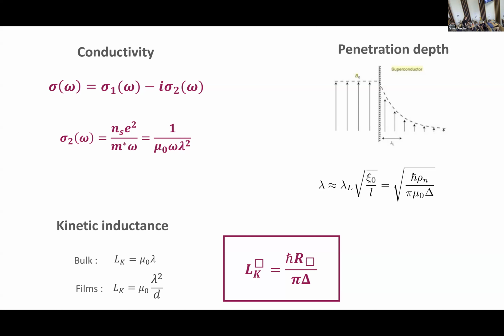And you may remember that if you put disorder in a superconductor, you start from a clean situation where the superfluid density is equal to the number of electrons within a factor. And once you plug in disorder, this quantity, the superfluid density, drops. This is given, for instance, by this evolution of the penetration depth, and you can change language and talk about kinetic inductance, the inductance of your superfluid, and you see that you have a direct proportionality. For thin films, you have the Pearl length, lambda squared over d, which takes into account the finite thickness. So the main property for application is this kinetic inductance, which rewritten in terms of thin film properties is proportional to the sheet resistance, and inversely proportional to the superfluid density.